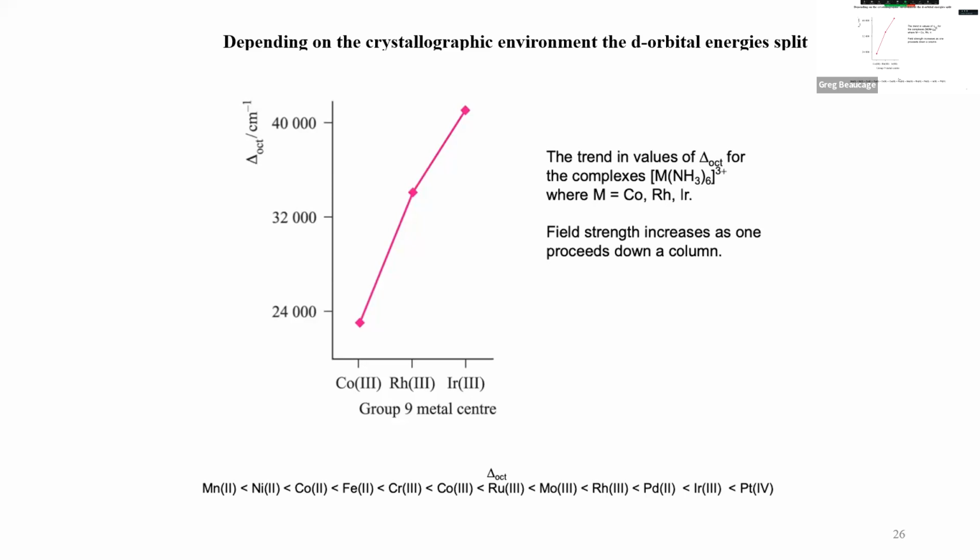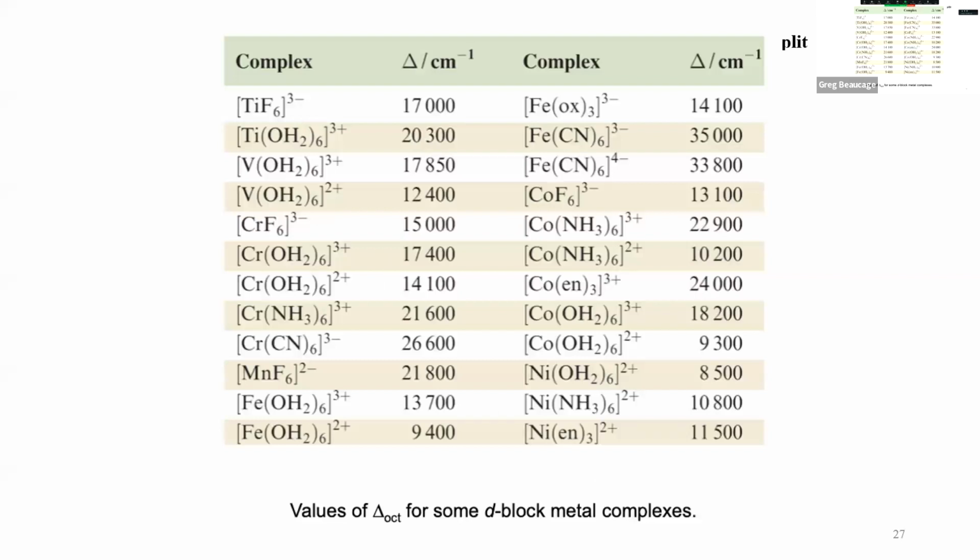This is just showing the same kind of dependencies on the periodic table position, like the electronegativity, and the octahedral energy. You measure this octahedral energy by doing UV spectroscopy. You shoot light through, it absorbs energy at this octahedral energy, and you get a peak in the absorption band. From that absorption band, you can go back and calculate what this is for the octahedral. There's a direct relationship between the octahedral and the tetrahedral, so once you measure the octahedral, you can calculate the other d orbital splitting energies. So anyway, let me get rid of this thing.